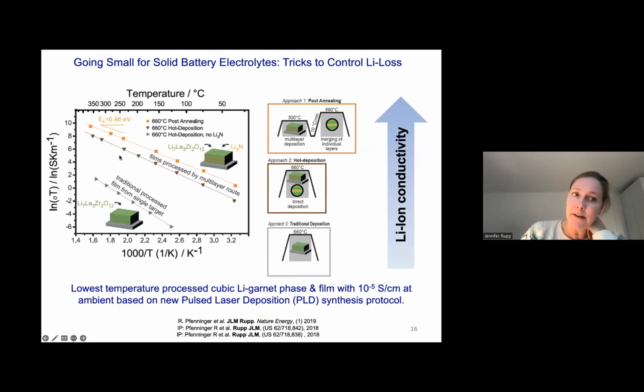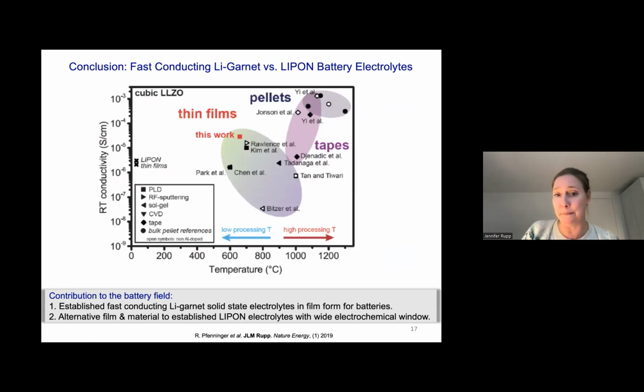Well, if you study now in an Arrhenius diagram the conductivity evolution of those films towards a traditionally lithiated film, so that's not this extra route with our multi-layers and then decomposing lithium nitride, gaining a very highly over-lithiated film, then you can see we always end up in the lithium loss phase. And if you choose our route, we end up actually in the high conductive lithium garnet phase. And that's why at the time we were able to get one of the highest conductivities in a thin film structure for the material.